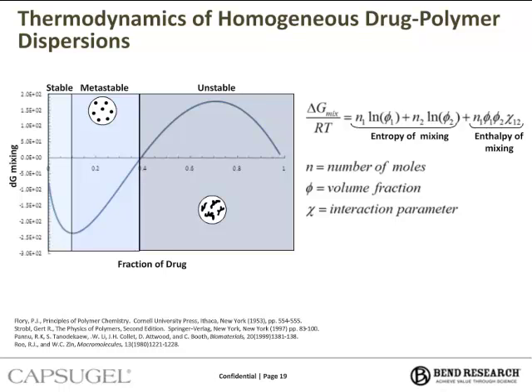So this next slide shows taking this a step further. This shows the thermodynamics of a drug-polymer dispersion. And we use Flory-Huggins theory to help us determine this thermodynamic relationship. And this is the same model used to predict solvent-polymer chemistry. Now, there are many assumptions that go into this model, but it's very pragmatic for its use. And it allows us to optimize drug loading as a function of process temperature.